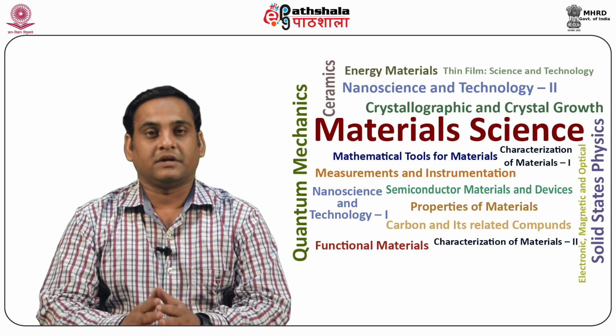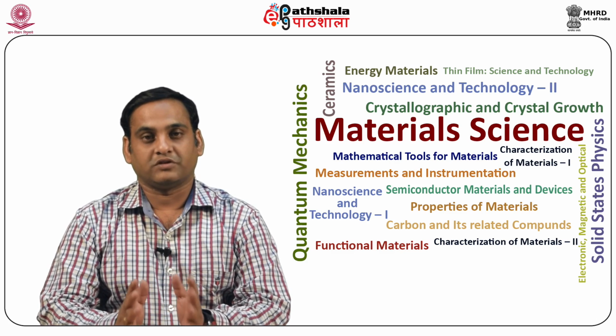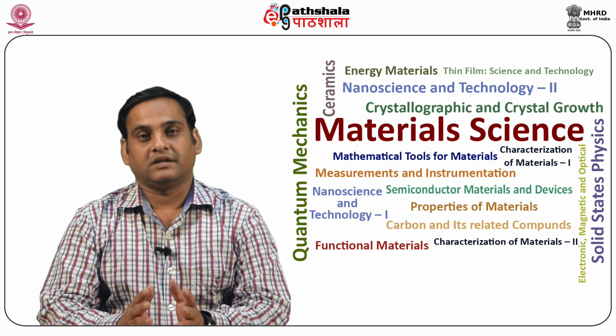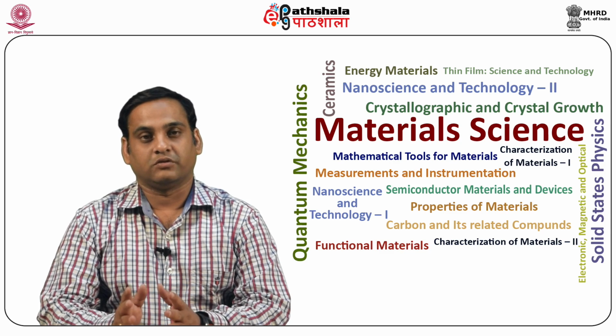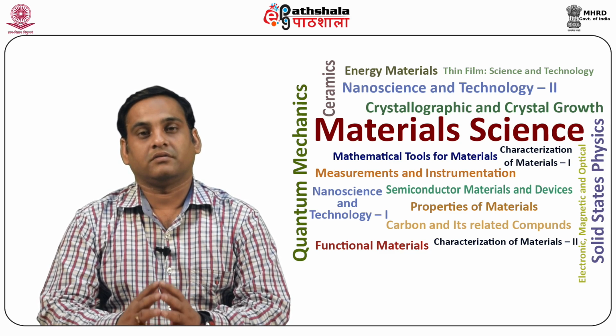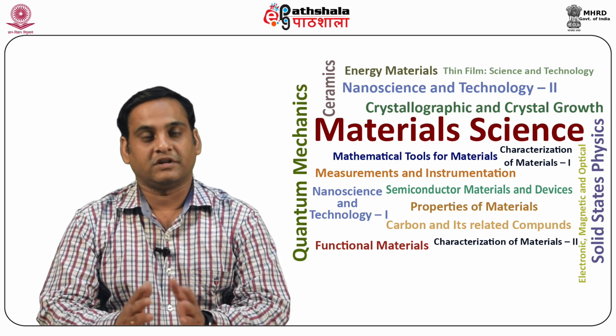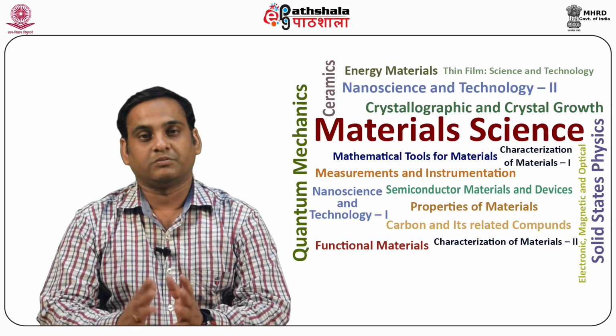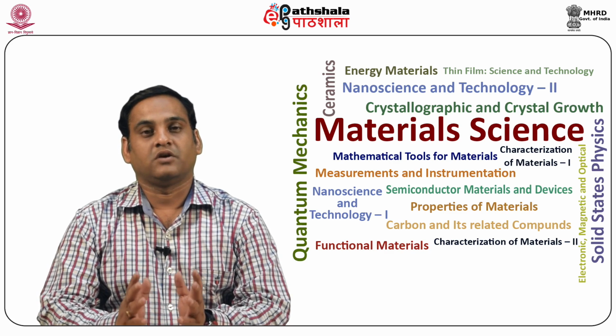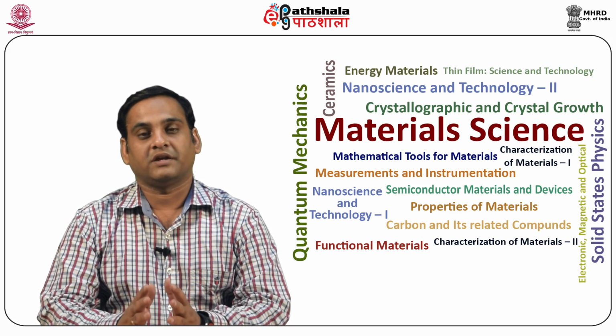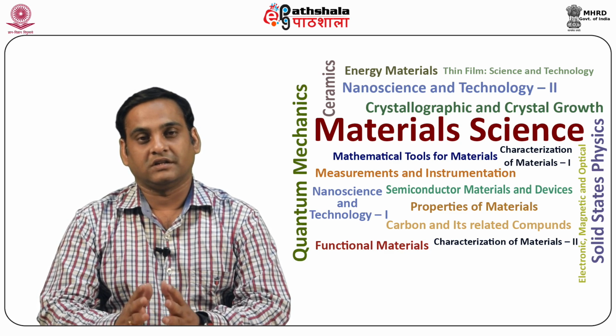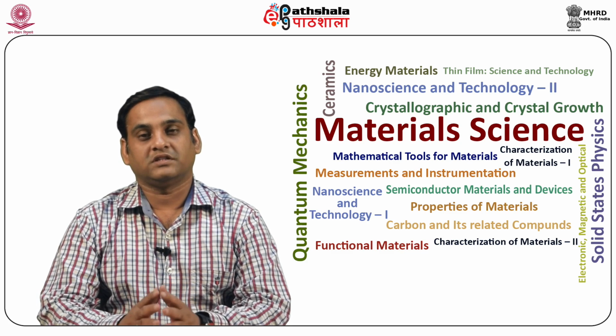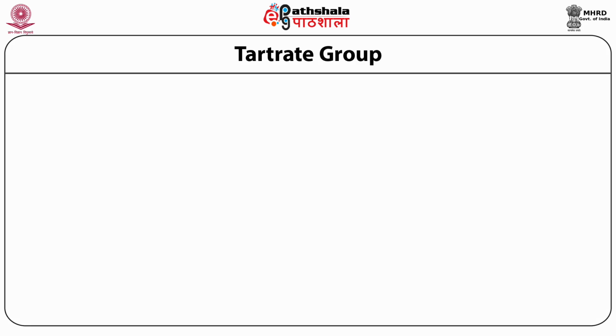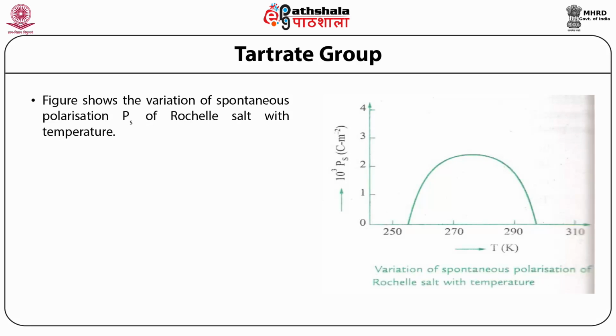Tartrate group. A typical example of ferroelectric materials of this group is Rochelle salt, which is the sodium potassium salt of tartaric acid, NaK C4H4O6 with 4H2O. This material was probably the first solid known to exhibit ferroelectric properties. It is ferroelectric only in the temperature range extending from -18 degrees centigrade to 23 degrees centigrade. Thus, the material has two transition regions instead of one. The figure shows the variation of spontaneous polarization PS of Rochelle salt with temperature.